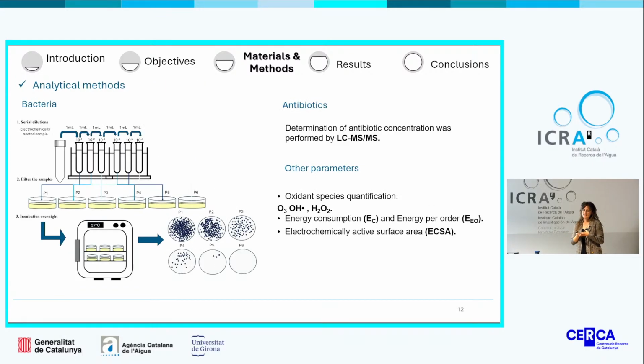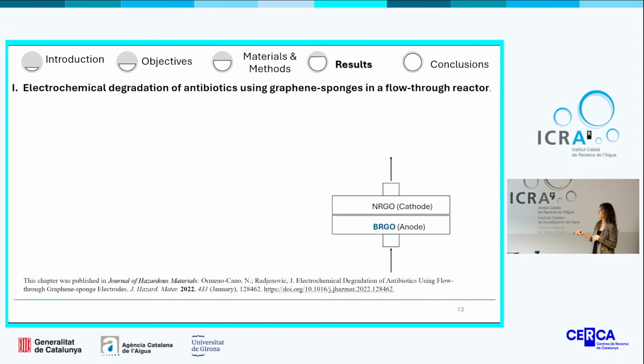The analytical method in case of bacteria, as it's shown in the presentation, was performed by serial dilutions, which were afterwards filtered and plated into agar plates. They were incubated overnight at 37 degrees, and after this we were manually counting the colonies. In case of antibiotics, the concentration was determined by liquid chromatography and mass spectroscopy. Other parameters, such as the oxidant species, the energy consumption and energy per order, as well as the electrochemically active surface area, were calculated as well.